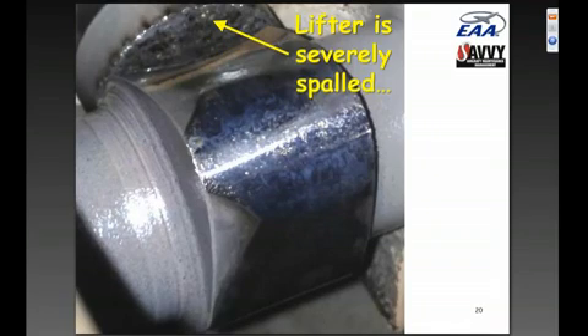And you can see that the lifter in this engine is in a severely spalled state. We can't see the whole face of it, but it's pretty clear that the entire face of the lifter is severely spalled. But this is a Continental engine, and it's really easy to change lifters. They're what are called barrel style lifters, and you can just remove them from the outside and throw a new lifter in, and it only takes about maybe an hour and a half of labor to change a lifter on a Continental engine. A lot less than that, obviously, if you've pulled the cylinder. If you pull the cylinder, it only takes a few minutes to change the lifter, and the lifters aren't terribly expensive. They're $80 or something like that. So if we saw a lifter like this, we would definitely want to change it right away.